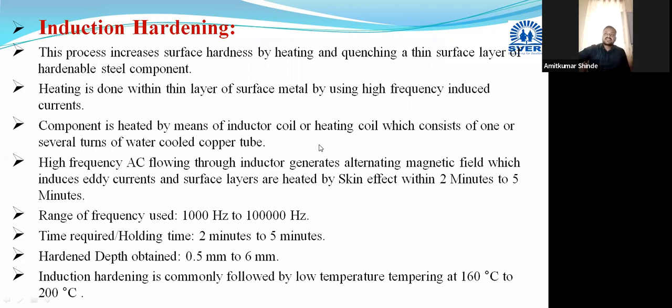The component is heated by means of inductor coils or heating coils, which consist of one or several turns of water cooled copper tubes. I will show you the diagram so that you will get a better understanding. High frequency alternating current flows through the inductor, which generates an alternating magnetic field.